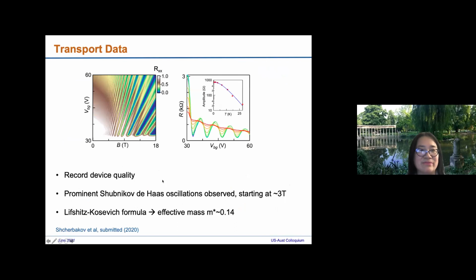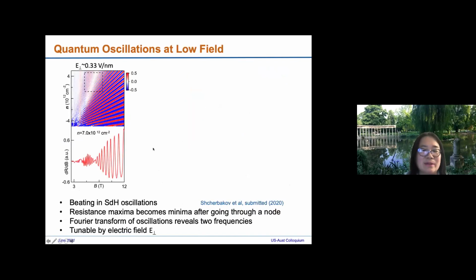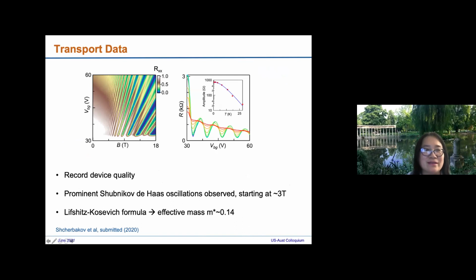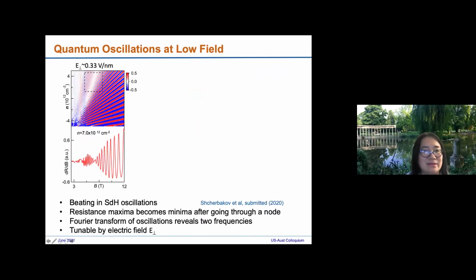Let me go to the next slide. We actually have very good mobility. I'm pretty proud to say we have mobility that's probably the best in the world right now, and so they show nice Shubnikov-de Haas oscillations and all that. But if we look at this quantum oscillation closely, for example by differentiating it, we see a node in this white line, which indicates zero amplitude in the oscillations.